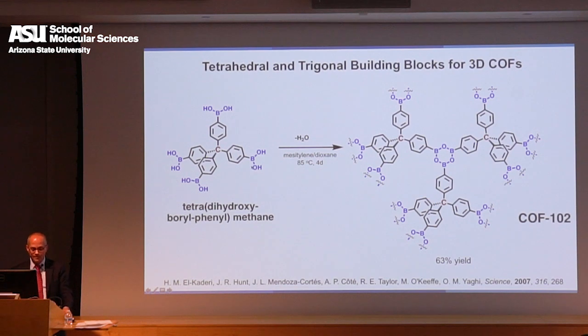Three-dimensional structures could be made by starting out with three-dimensional four-connected tetrahedral, let's say, building units, and dehydrating that to make triangles as links and the organic links that you put in. The nice thing about COFs is that, unlike MOFs, what you put in does not change. They're only linked together through one bond or one form. They don't really decompose and come together again. So they're very predictable. And because Mike had worked out which nets were going to produce from which building units, it was easy for us to link them together and then look at the powder diffraction and match it to the simulated powder diffraction that we got from the predicted structures. That's why you see Mike's name on some of these COF papers.